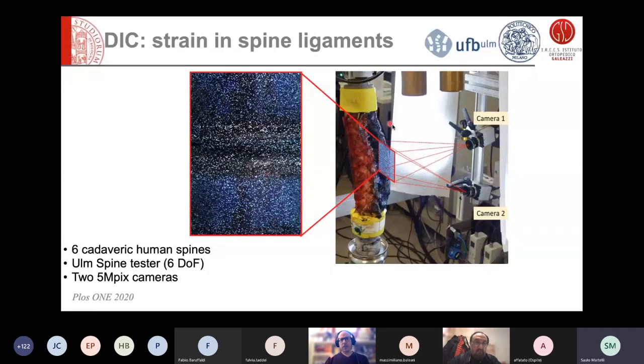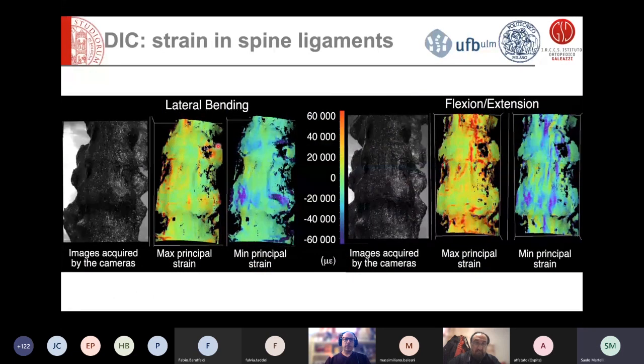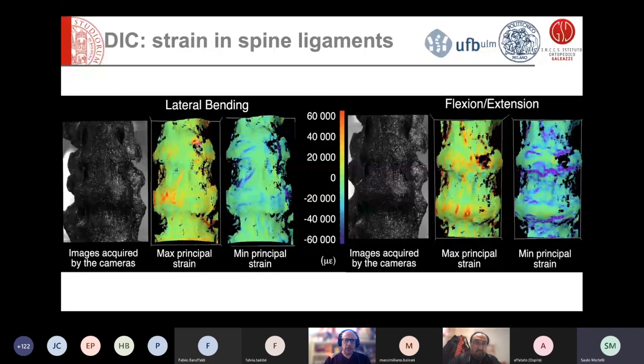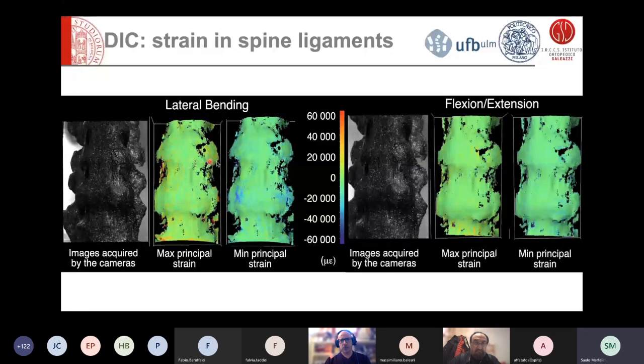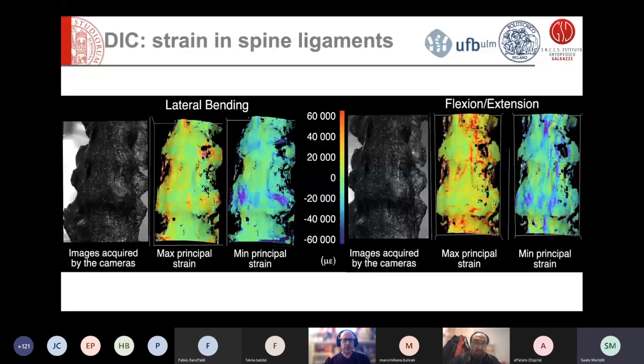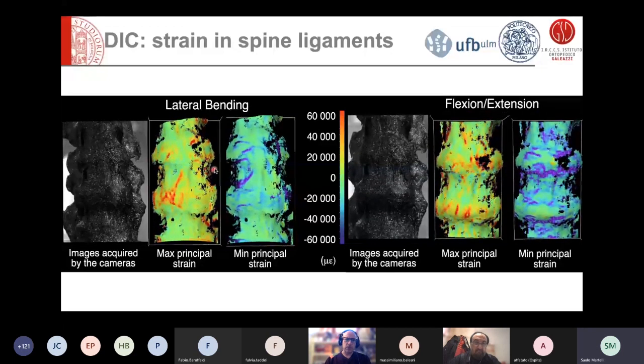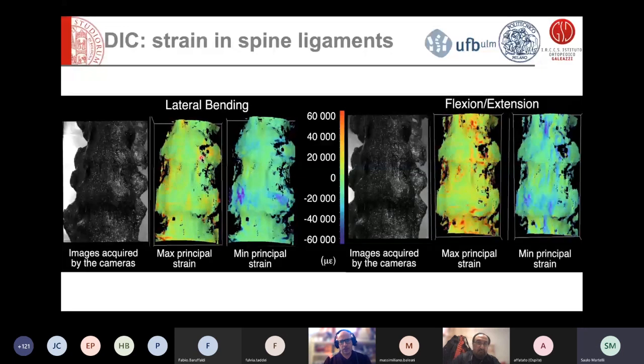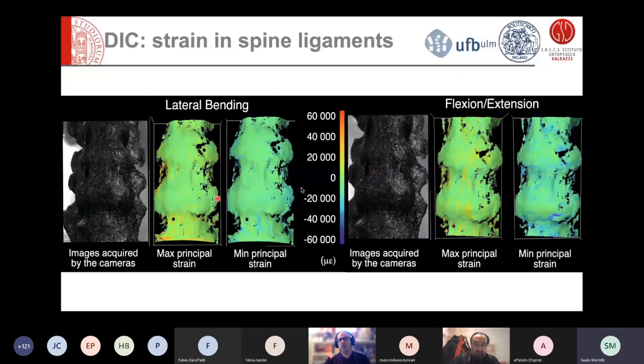We are doing also a lot of work on the spine because DIC is very good at measuring what happens in soft tissue. This is a project in collaboration with Aki and Wilke in Ulm, where we were testing cadaveric spines, and we're using our low-cost version of the DIC and their spine tester. Here you see the deformation in the anterior spine ligaments in terms of stretch, tensile and compressive strain. You can see the individual fibers of the ligament. You see the effect of the bulging of the underlying disc. We could even observe the effect of the osteophytes in terms of local peaks of deformation here and there.